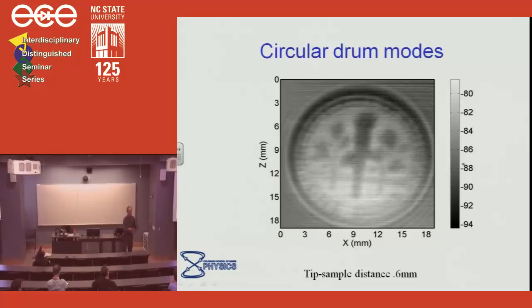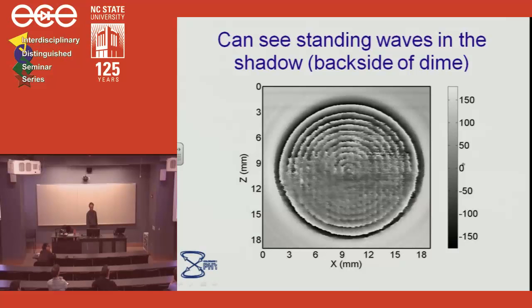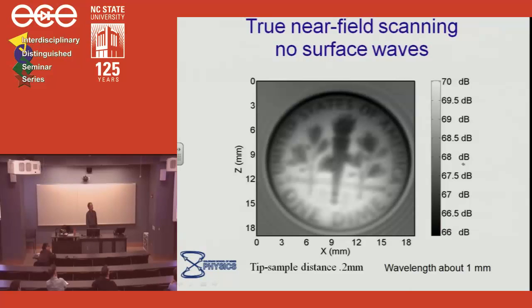Now here's an example where the probe tip is about a wavelength away from the surface, and that allows you to create propagating waves on the surface. Now, if I move the probe tip closer, to within a fraction of a wavelength, it turns out that the millimeter waves coming out of the probe do not couple to propagating waves. They couple directly to the evanescent field. And that's what is really called near-field scanning. So here's what you get in that case, and you'll see that those circular drum modes go away. This is an image produced entirely with the evanescent field on the surface of the dime. And this is the thing we modeled with finite element.